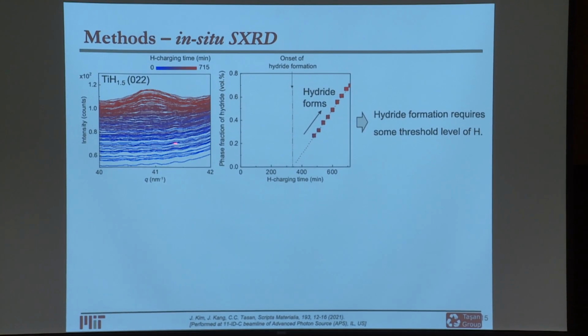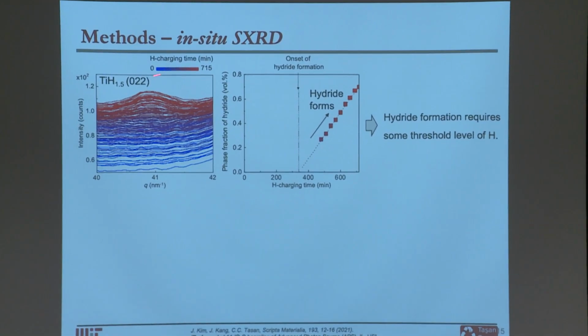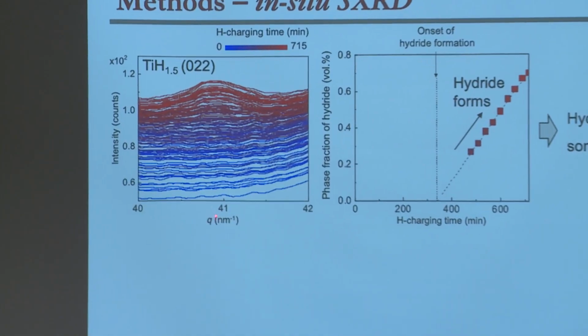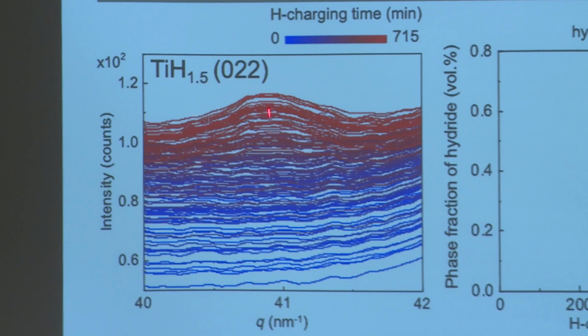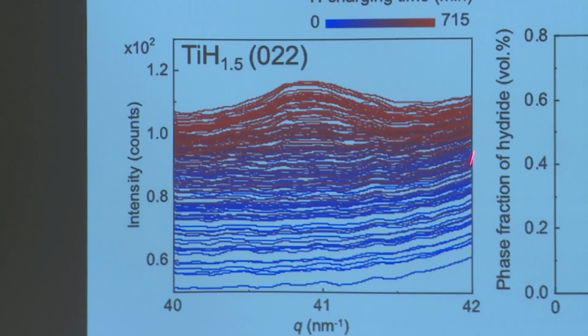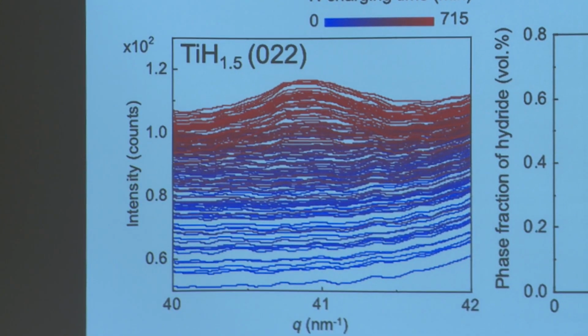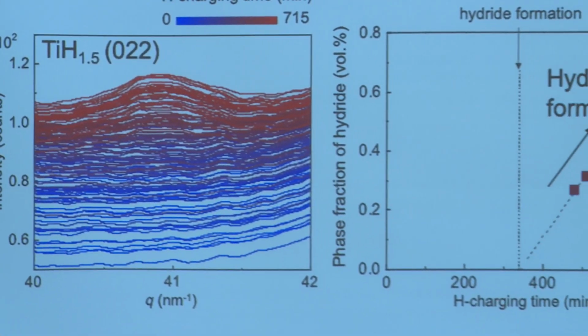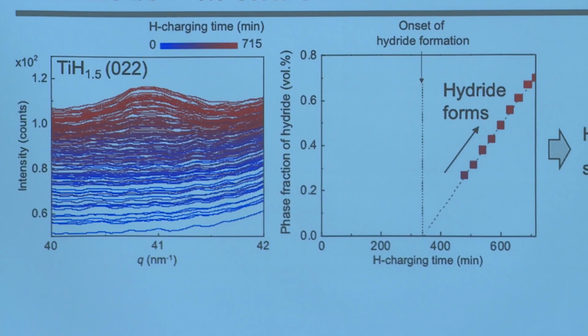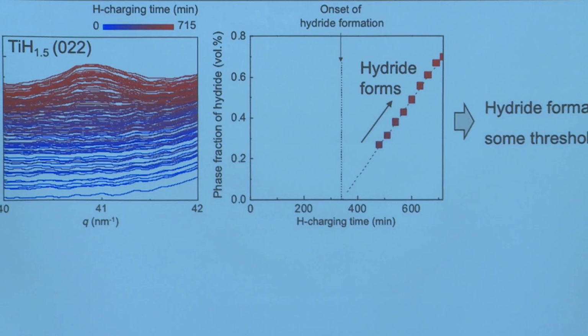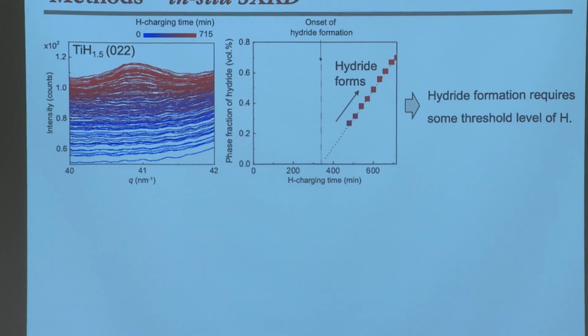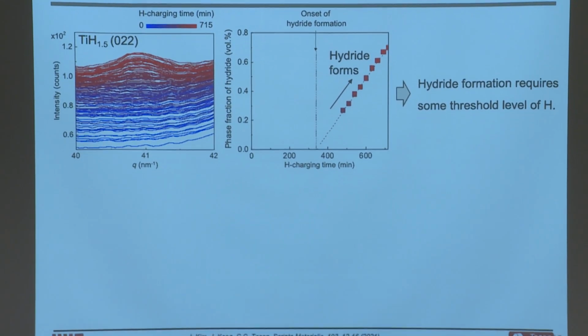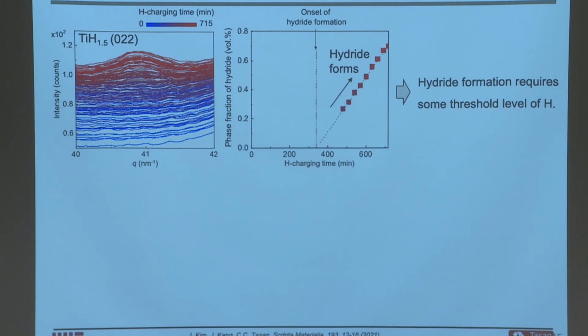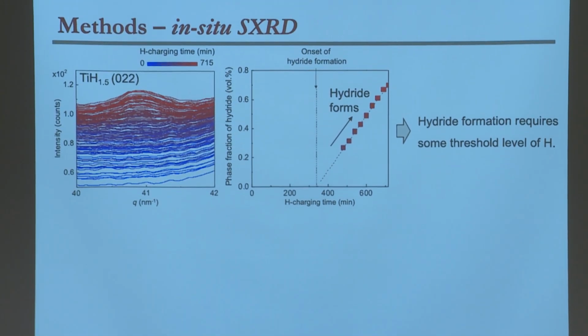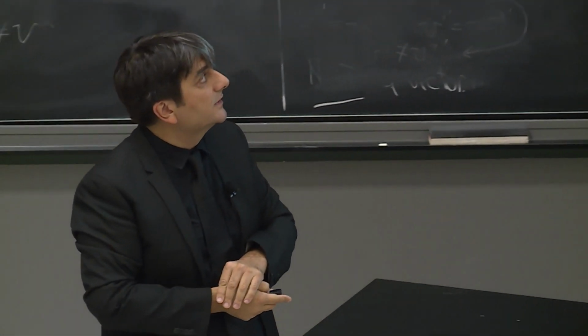So if you are doing it in synchrotron, then you can also do this in a time-resolved manner. So in other words, you can take a look at how this peak evolves as a function of time, which you can use then by doing Rietveld refinement to say something about the formation kinetics of these type of hydrides. Here, we are not seeing anything, so there is no spatially resolved map. I don't have a microstructure micrograph that shows where hydrogen is, but at least I see when hydride starts forming very accurately.